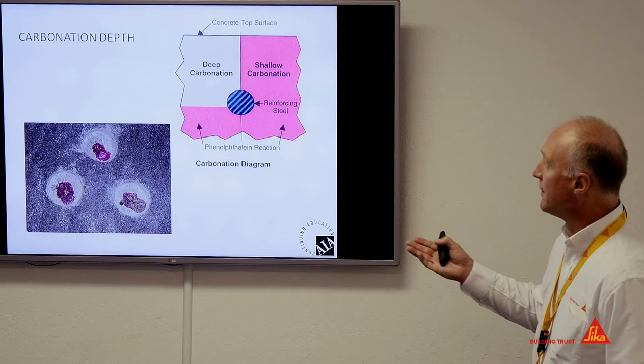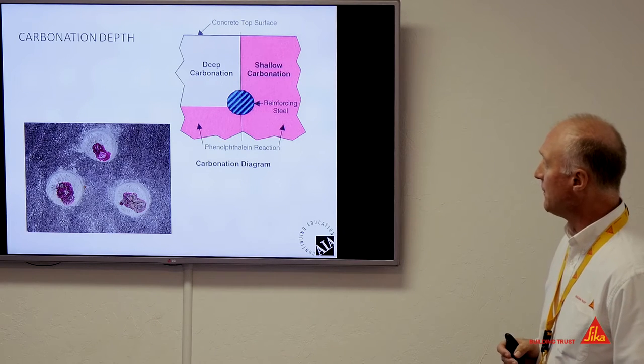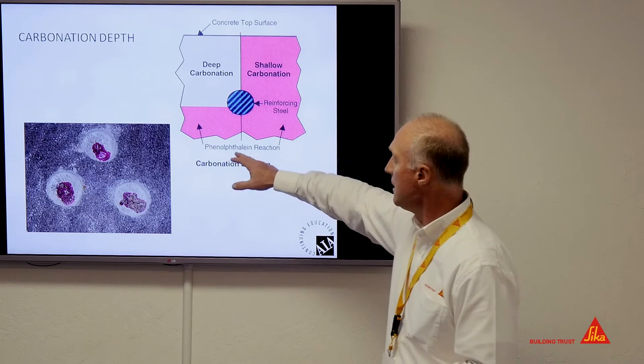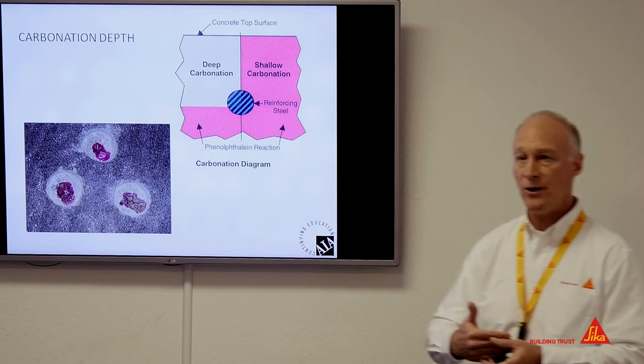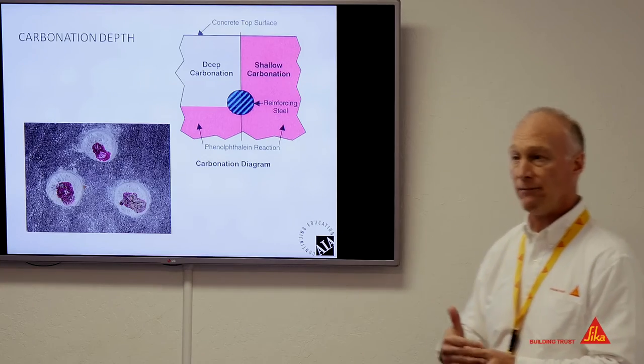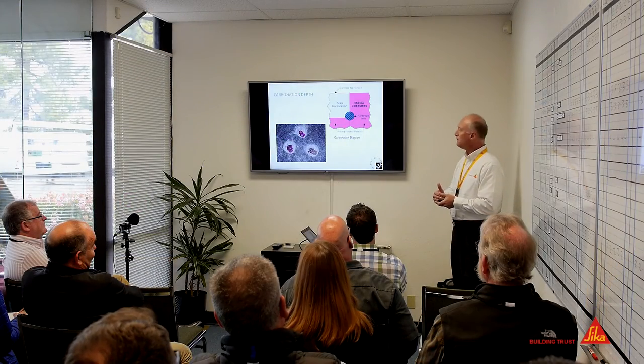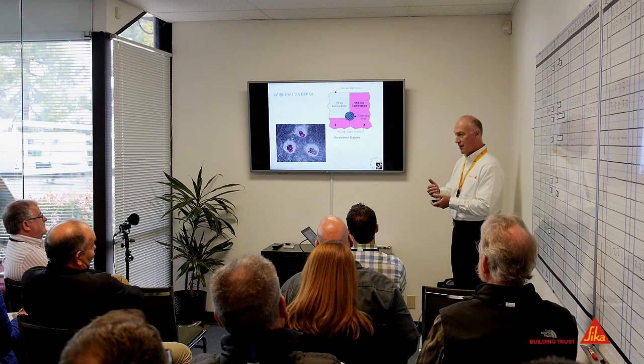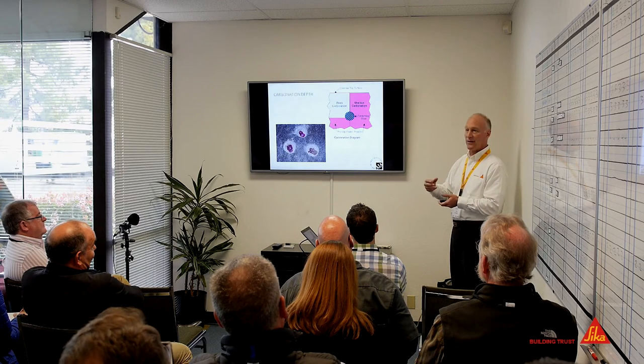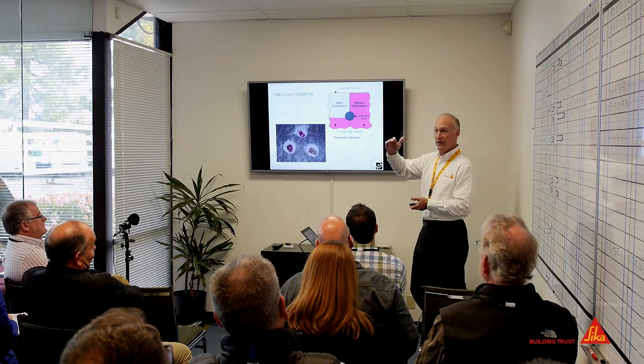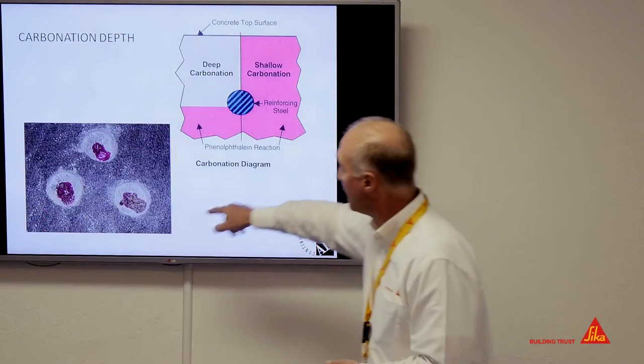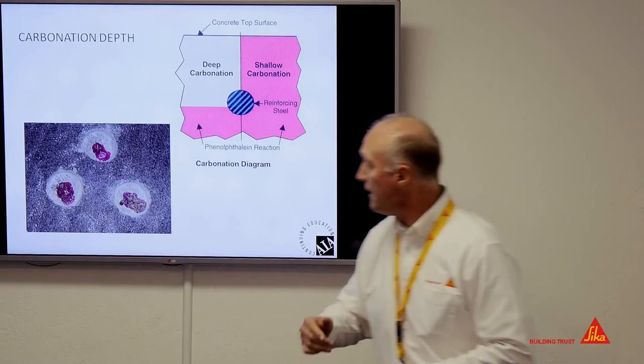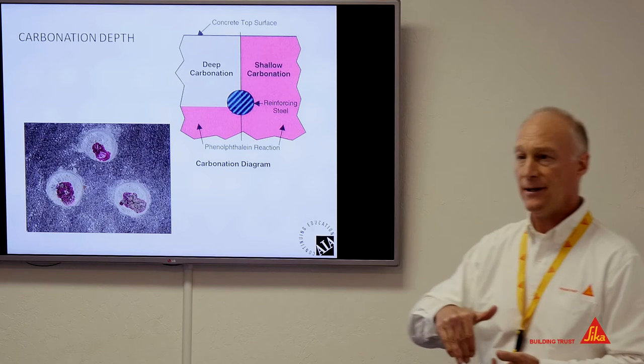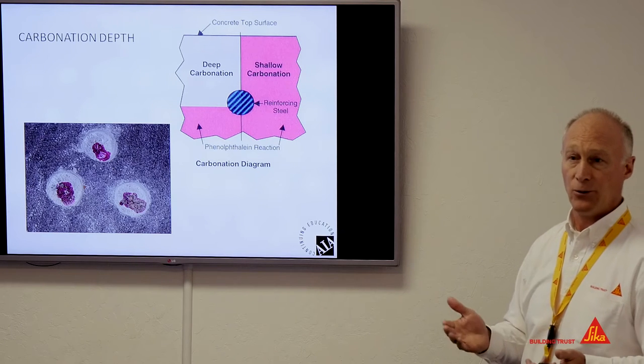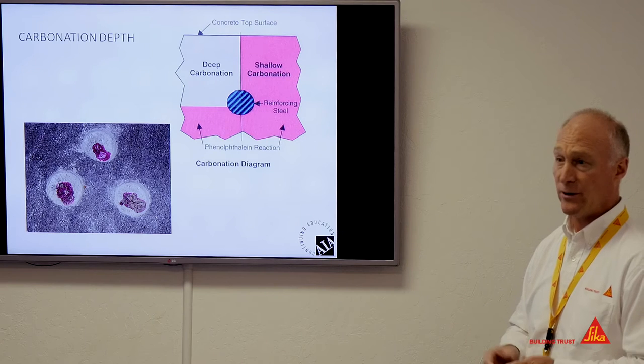And then the other test, a lot of times we'll see in concrete, is a very simple test. They'll take a solution of phenolphthalein, and if you apply that to some concrete that's been broken, relatively soon, when you spray this solution onto the concrete, if you get a purple reaction, that tells you that the pH is high, which means that the steel is in a good environment. If it remains clear, like it does here, then the pH is low. And if the pH is low, then the steel is now in a more aggressive environment.